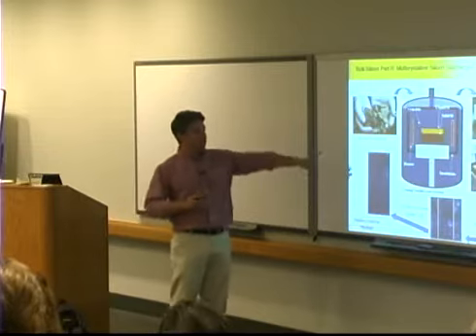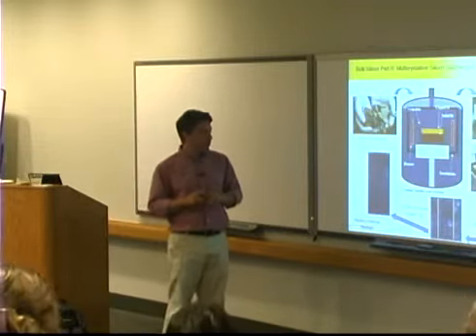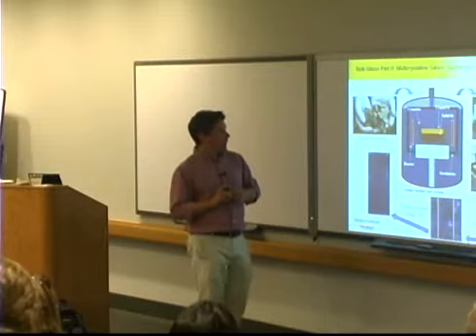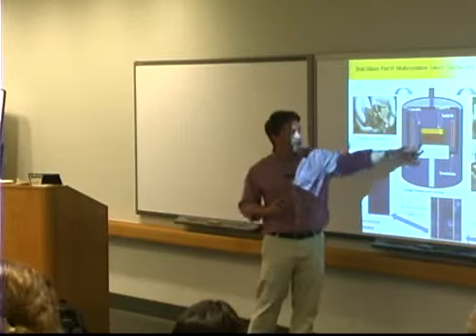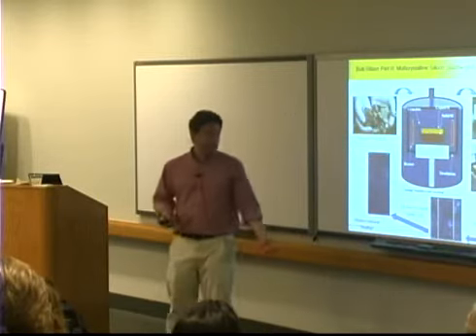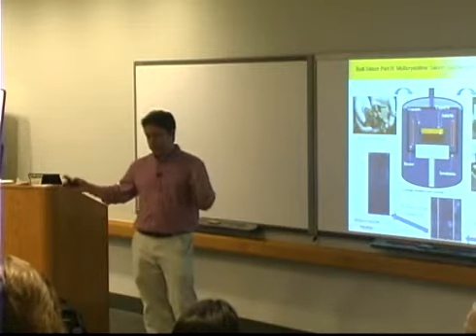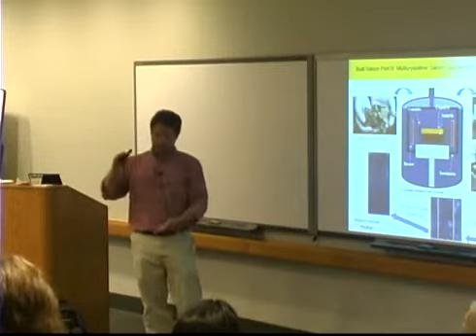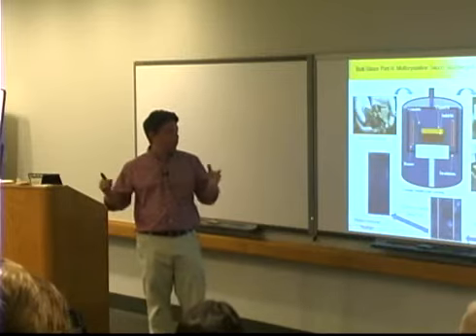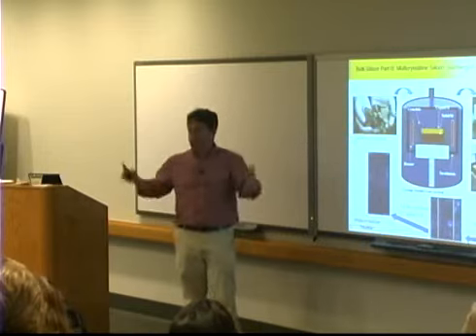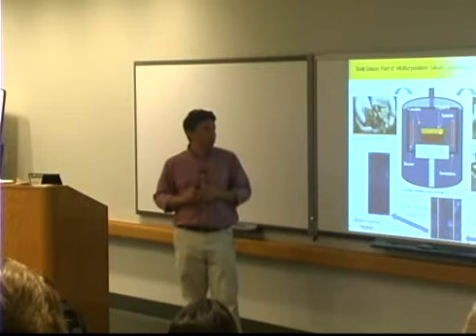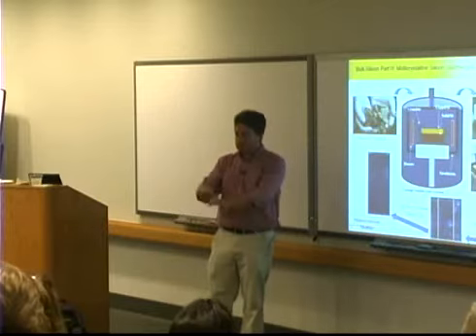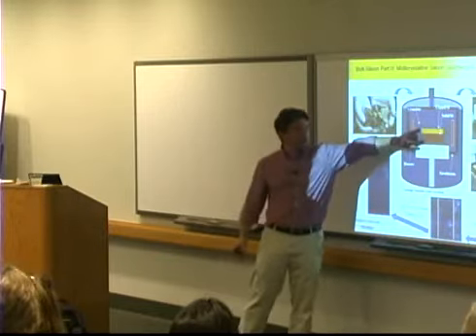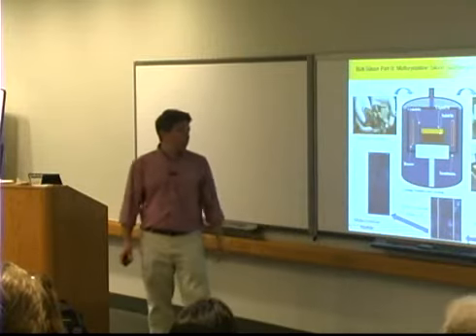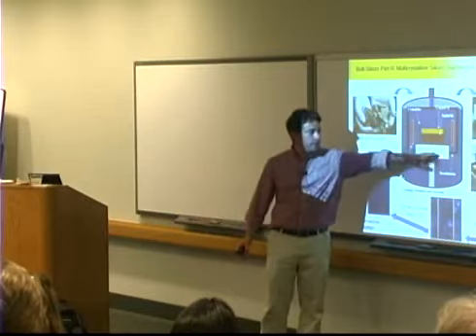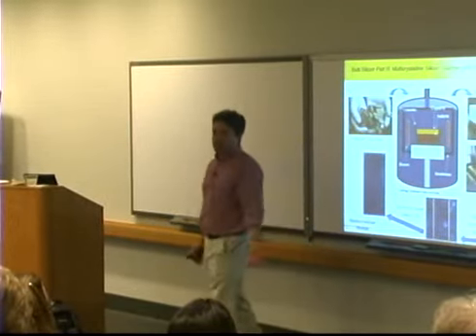So this is multicrystalline casting, and this has been around for 30 years already. It's also conceptually very simple. You get a box, in this case a quartz crucible. Today the standard is a little less than a meter square and maybe half a meter high. You fill it full of chunks of polysilicon, just stack them in there. You put it inside the furnace. You melt all that down to a liquid level that's typically maybe 2/3 of the height of the crucible. And then you start extracting heat from the bottom, and you just grow a relatively planar interface straight up.